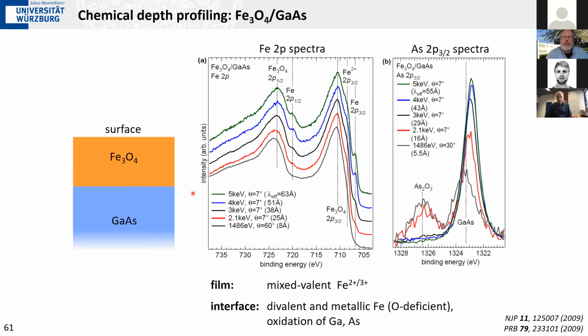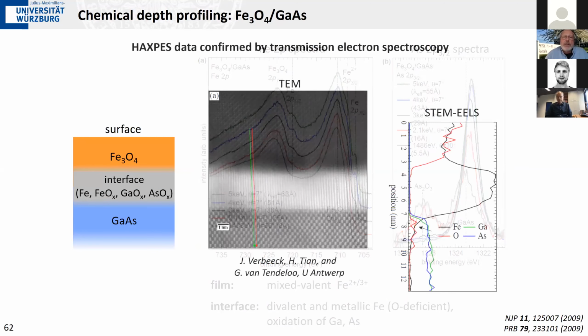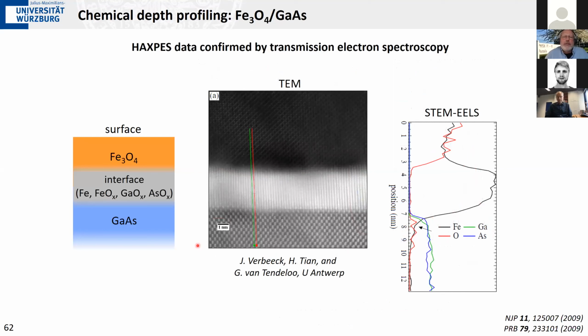So apparently at the interface, the arsenic gets oxidized, and at the end, you get a picture where at the interface, oxygen penetrates from the magnetite into the gallium arsenide, so it oxidizes gallium and arsenic, but then deoxidizes the iron, so that you are left with iron oxide and metallic iron. And so you have a lot of chemistry going on in the interface that would impede the actual functionality in